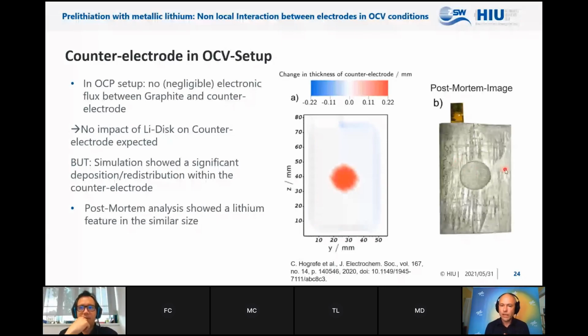So what was going to happen? What was going to happen was that since the lithium disk was dissolved, we had a concentration gradient in the electrolyte. The lithium ions were diffusing to the counter-electrode, where due to the larger concentration, you suddenly were not in equilibrium anymore. You could deposit lithium, and since you have to make sure that the charge neutrality is conserved at the other part, namely here at the border, lithium had to be re-dissolved into the electrolyte so that the full counter-electrode kept charge neutral. And this lithium then was traveling back to the graphite and was intercalating there. So in total, no lithium was really taken away from the counter-electrode. It was just reshuffled in the counter-electrode.